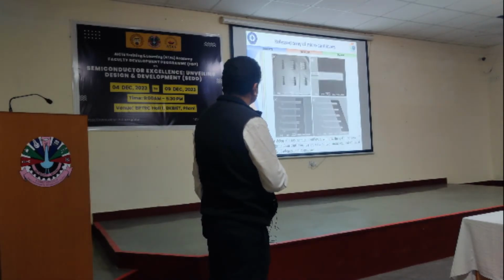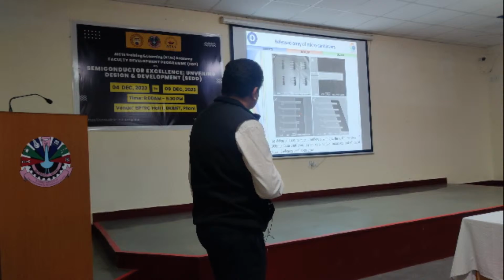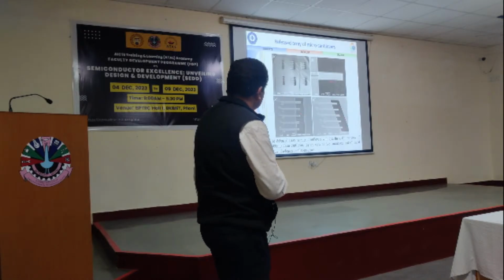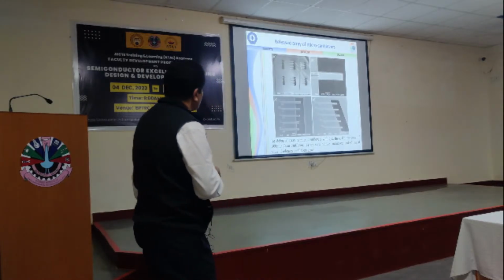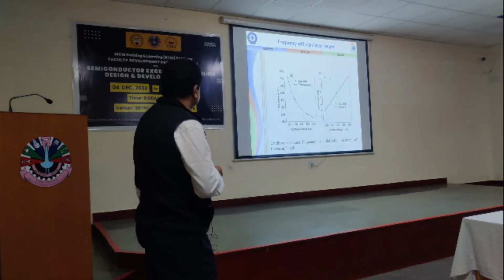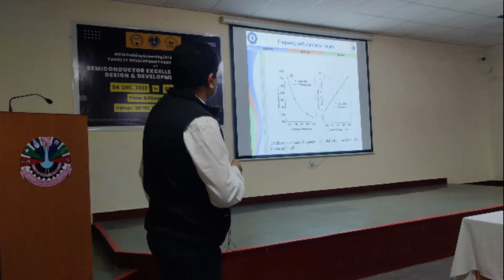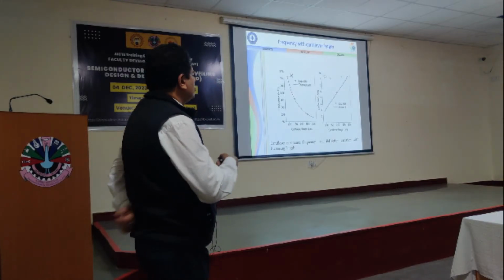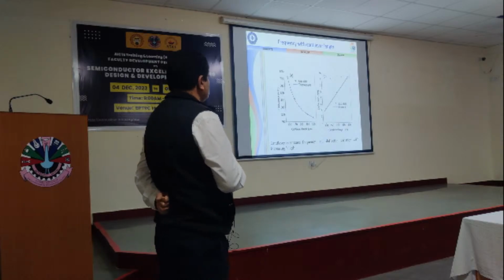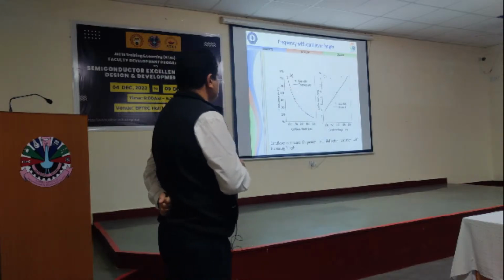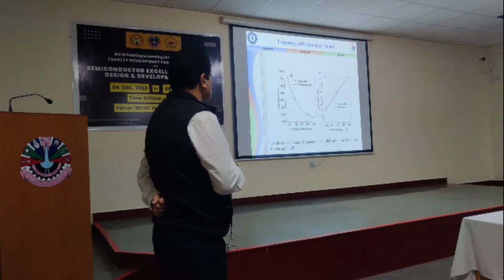And to improve the step coverage. These are also various micro cantilevers made here. The microstructures were made here. It is a single microstructure. These are the array of microstructures, and these are the 5 micro cantilevers of different dimensions. Then we did the frequency versus the cantilever length. Means their length was varied and their resonance frequency was measured. So we can see data here that as we increase the length of the micro cantilever, its resonance frequency decreases.